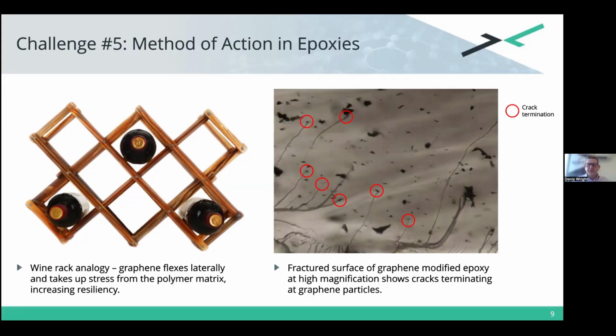That means that it is taking up some of the stress. And what we've got on there is a picture on the right-hand side of a solid epoxy polymer cured with a polyamide. There is just graphene and just polymer A plus B in there. And when we put that under stress and broke it, what we found was that the graphene stopped the crack lines through the polymer. Now, that in itself is an indicator. It's not a conclusion or the panacea of all woes or anything like that, but it's a very strong indicator about how graphene is working to take up the stress within the coating.